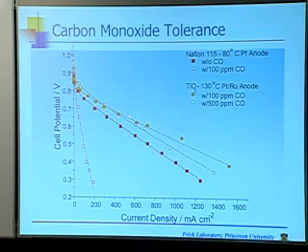We're doing better. We add in some more CO. We go up to 500 parts per million. And there's a slight decay in the performance you notice there. But still, we're outperforming there. And you'll notice, by the way, for the first time, that not all the data up here in the Tafel region falls on top of each other. That is, we are playing now with the charge transfer kinetics by CO poisoning our surface.